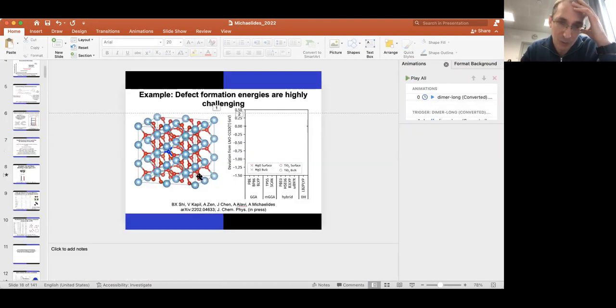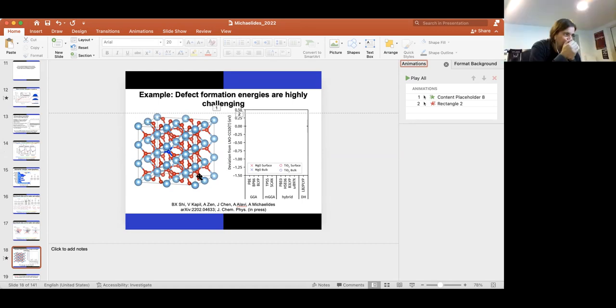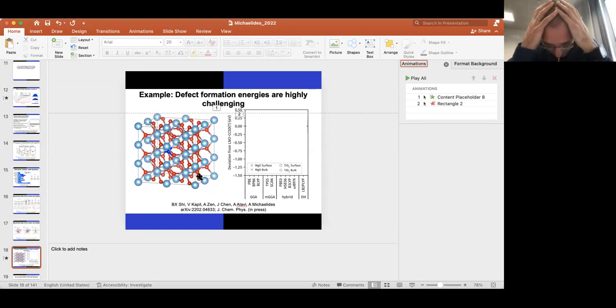They are very sensitive to a lot of parameters. So I guess you can see this slide again. Mm-hmm. So TiO2, I think in mentioning TiO2, you've picked the most painful and the most sensitive system, and so with TiO2, there are very significant relaxation effects. The semi-core electrons can be important. So if you're using pseudopotentials, you really need to check that a sufficient number of electrons are treated as valence.